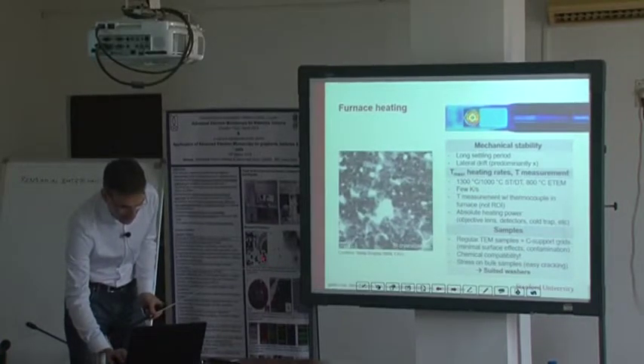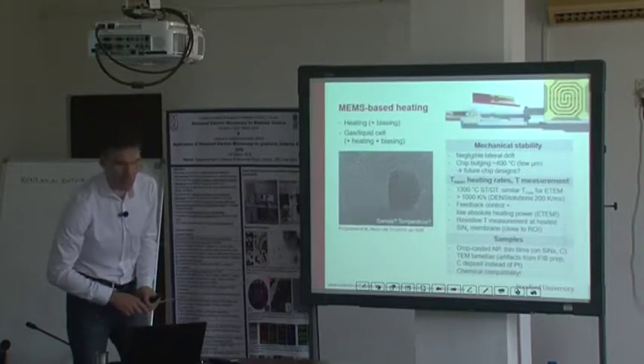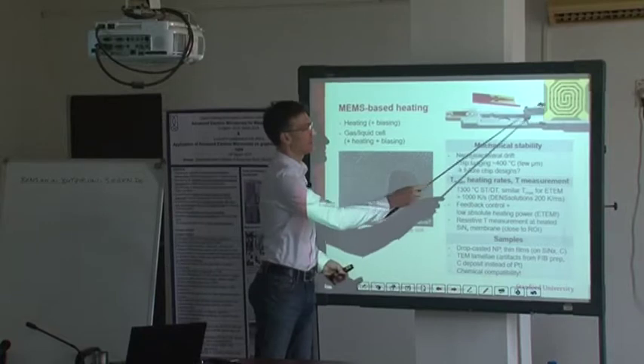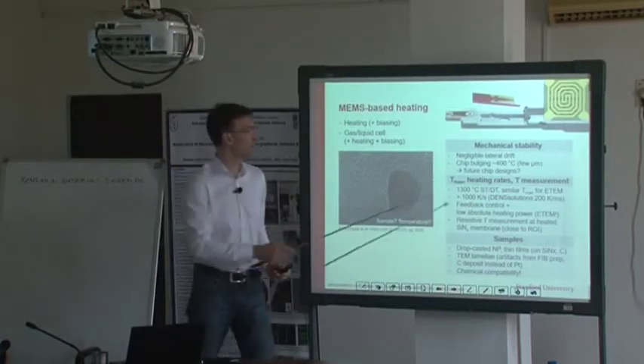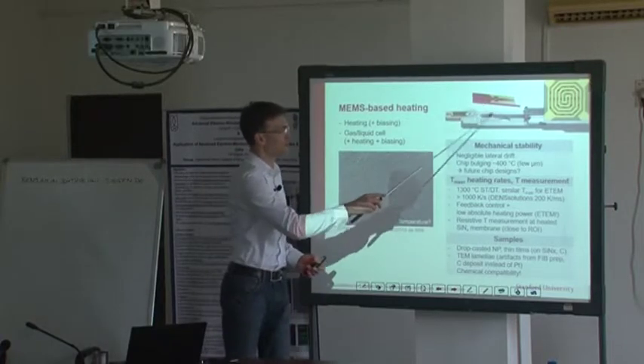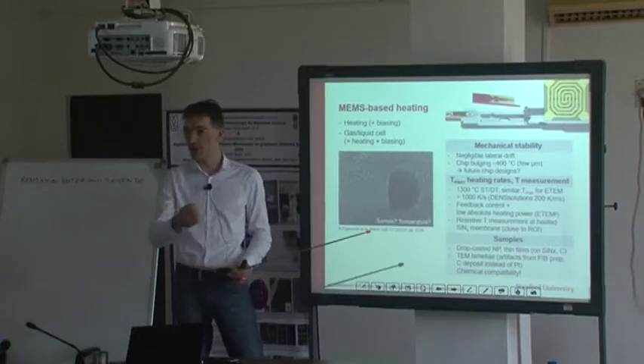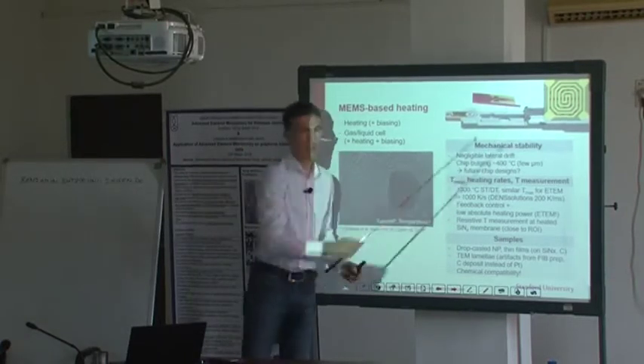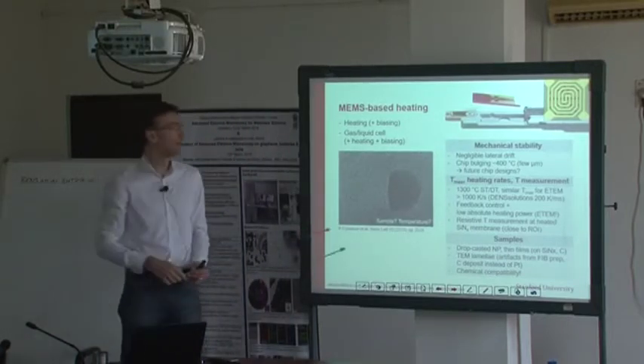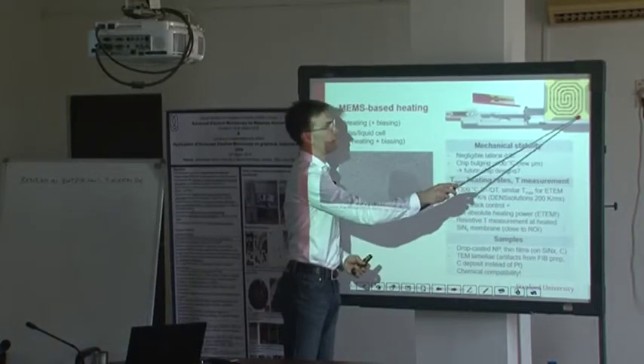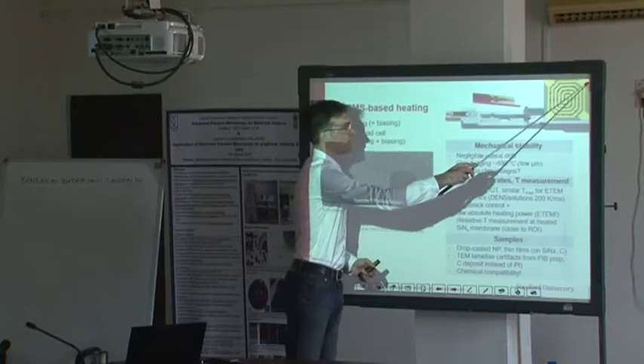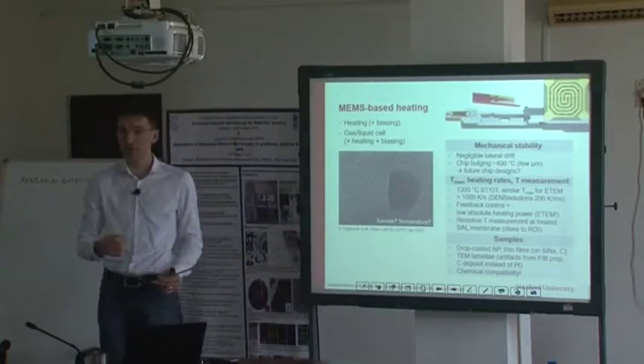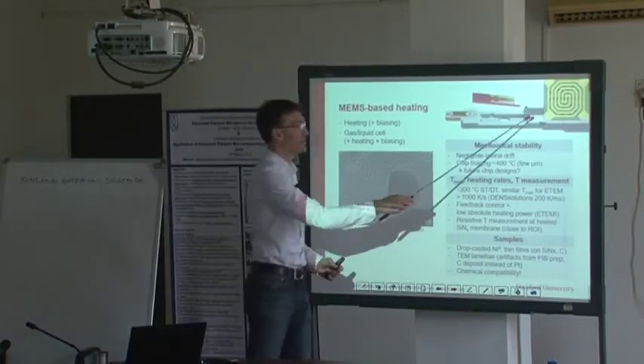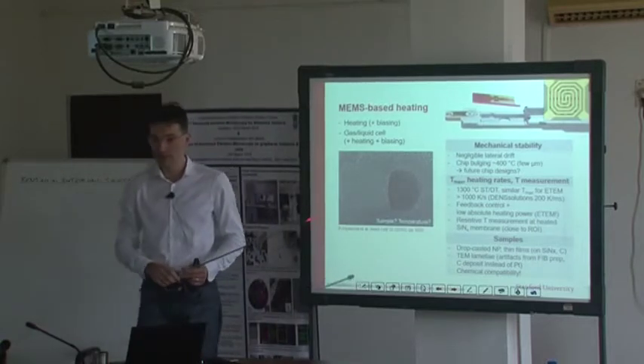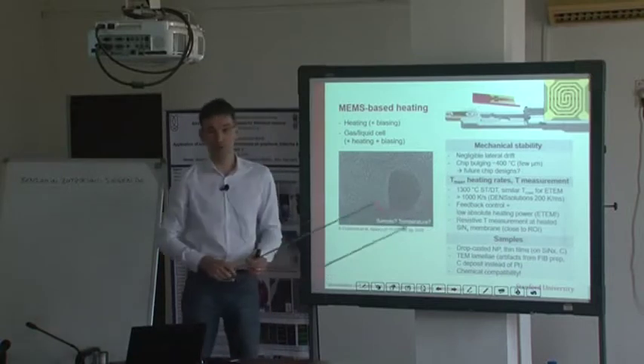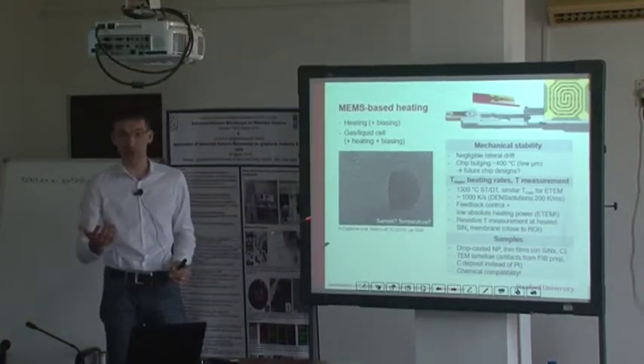There's another way to heat in a transmission electron microscope, and this is to utilize MEMS-based heater chips. In this particular case, this is the DENSsolutions heater chip. You introduce this heater chip, you contact it, and you simply run a current through a metallic nanostructure. Due to the resistivity of the nanostructure, heat evolves. They apply a current to introduce the heat, and with another 2 ports they measure the resistivity of the structure. The resistivity depends on the temperature, so they are able to calibrate this temperature. For high vacuum experiments, this preset temperature corresponds very well to the measured temperature which we got from our diffraction experiments. So this is quite good.